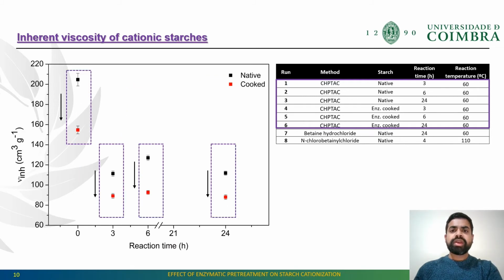Further, talking about the inherent viscosity of native and cooked starches, undoubtedly the inherent viscosity decreases with the enzymatic pretreatment, as cooked starch showed lower inherent viscosity compared to native starch. This decrease can be justified due to the cleavage of the 1,4-alpha-D-glucopyranosyl linkage of amylose and amylopectin, which reduces the degree of polymerization. In fact, the hydrolysis of starch granules due to the high alkaline and high temperature environment may also be one of the reasons for decreasing the degree of polymerization.